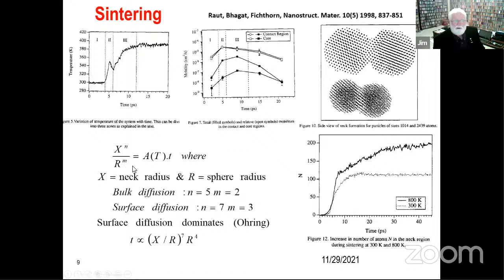There's a classical formula here. If this is a neck radius and this is the spherical radius, defined here, sintering occurs mainly by surface diffusion. There can be a bulk diffusion element to it, but usually surface diffusion. So if we rearrange this equation, the bonding time between two small particles can be expressed in this form, where it's proportional to the fourth power of the radius.